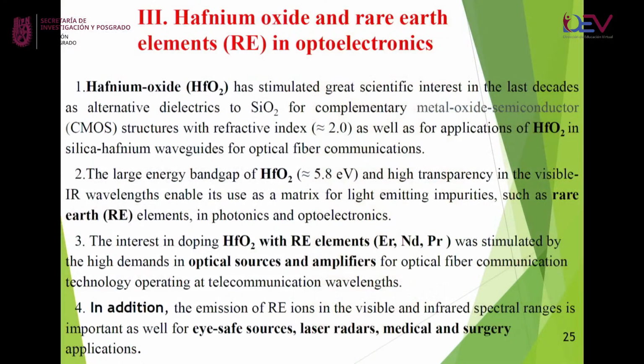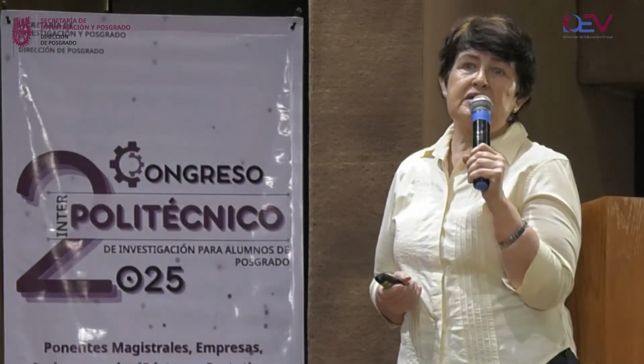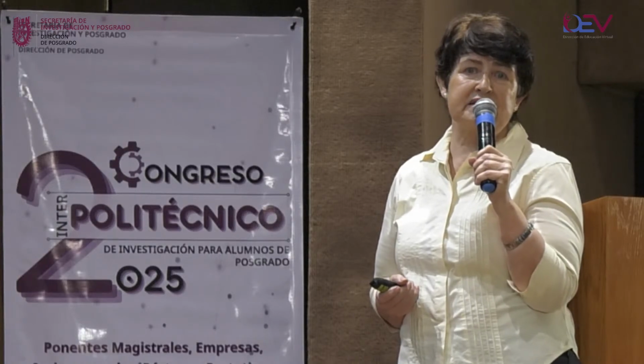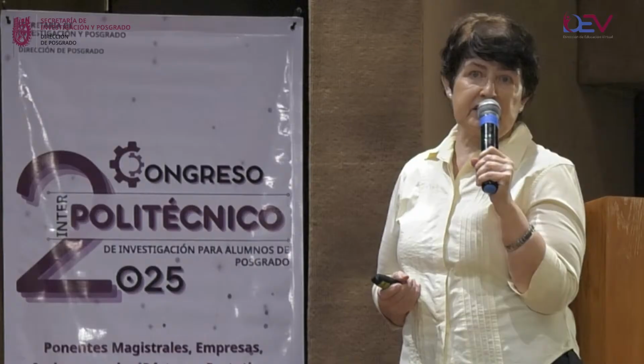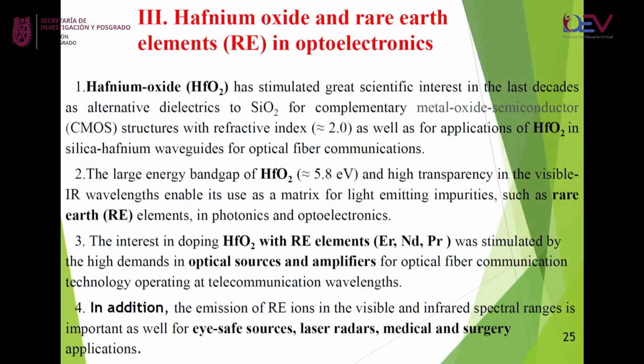We use hafnium oxide, interesting because this material has a large band gap, 5.8, but is transparent for the whole visible range. And due to this transparency, this is a very interesting matrix for rare earth atoms. Rare earth atoms being investigated are erbium, neodymium, praseodymium. All these atoms create separate levels needed for optical sources and amplifiers for optical fiber.